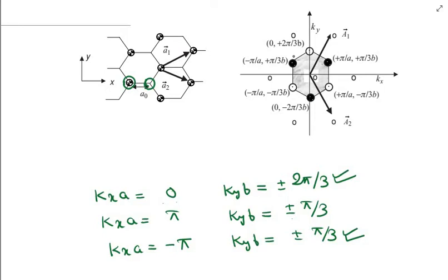Now these 2 K points are not equivalent, and why they are not equivalent is exactly the same reason that this atom here and this atom here are not equivalent, because they do not see the same crystal structure. So that is why these 2 atoms basically constitute one unit cell, because this atom and this atom are not equivalent atoms. Similarly, this point and this point are not equivalent points, and these basically constitute the unit cell in the reciprocal space.